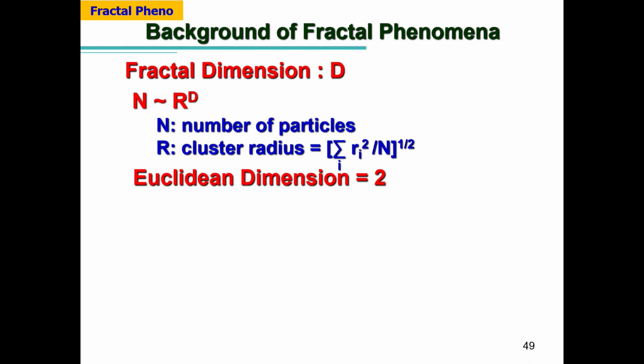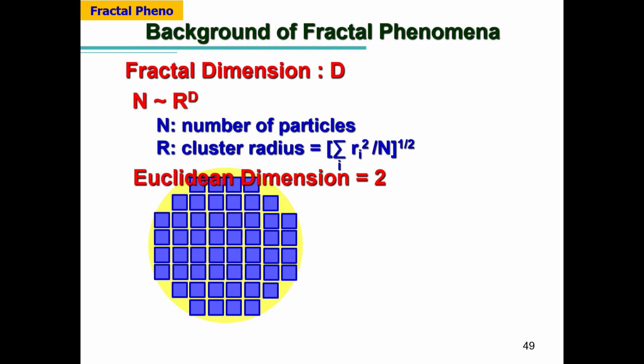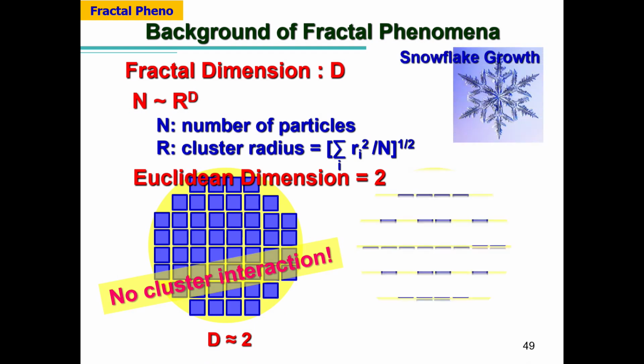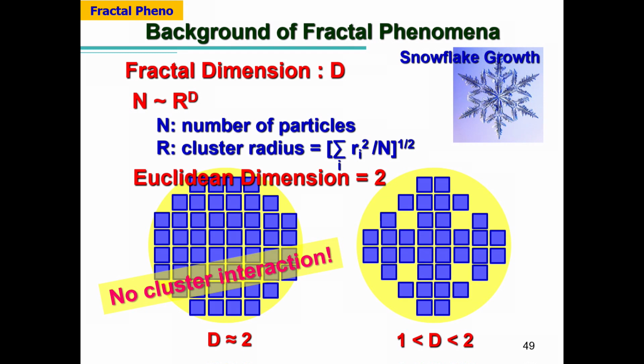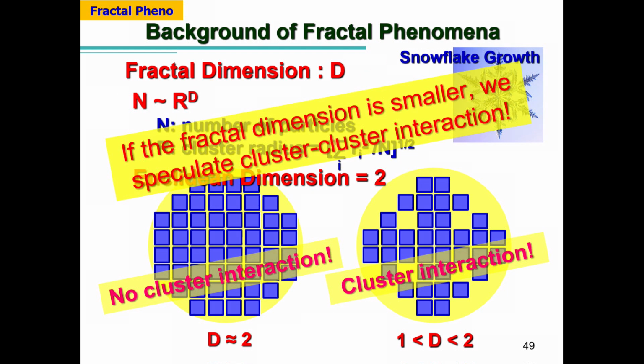So a fractal dimension, how can we determine it? This shows the two-dimensional case. So how many numbers, roughly R to the power of 2? So Euclidean, completely filled in, is 2. However, if you create a snowflake-like structure, okay, some particular points must be eliminated. So this is the cluster-cluster interaction. If you find the cluster-cluster interaction, D is observed to be less than 2, okay? So as long as we can measure fractal dimensions smaller than particular values, we speculate the cluster-cluster interaction at least.